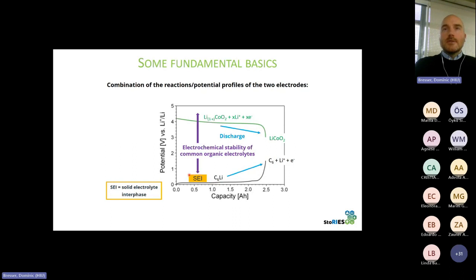The SEI is a term that is frequently used, and we know most of the components, but it's still not fully understood how it's working and how we can fine-tune it. So electrolyte additives, for instance, that might have a positive effect on the stability of the SEI: the search for such successful, efficient or effective additives is still a kind of trial and error chemistry frequently. So there have been approaches to organize this a bit better, but still frequently people are trying different chemicals and seeing if it works or doesn't.